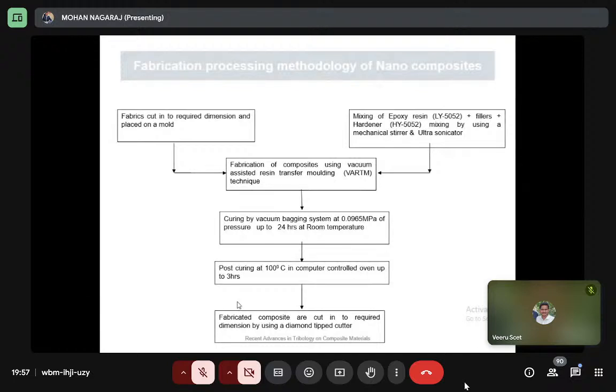Fabrics are cut into required dimensions and placed in the mold, and the epoxy resin is mixed with the filler. Epoxy is a general adhesive, similar to what you use for joining pipelines. These are manufactured using the vacuum-assisted resin transfer molding technique, then cured by a bagging system at 0.0965 megapascals for up to 24 hours at room temperature, and then post-cured in an autoclave or controlled oven at up to 100 degrees Celsius for up to 3 hours. Fabricated composites are cut into required dimensions using a diamond tip cutter. So after this is the schematic diagram.